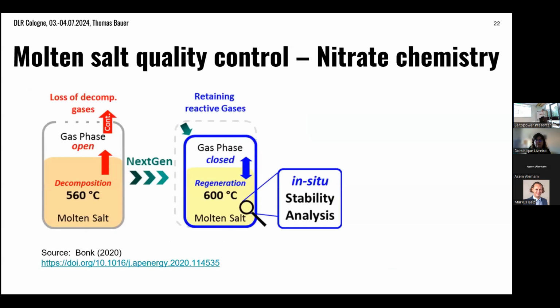So we saw this idea from Frerk before. If you want to stabilize the salt, we think it's a good idea to close the atmosphere, to not release oxygen and nitrogen oxides, but rather keep them in the system. And in this way, you can stabilize the salt. This has also been published, and you can find the publication, and it has been demonstrated in the lab, not in large scale so far. The largest scale experiment is the one Frerk showed up to now. I think there's no other experiment with solar salt at this high temperature yet.